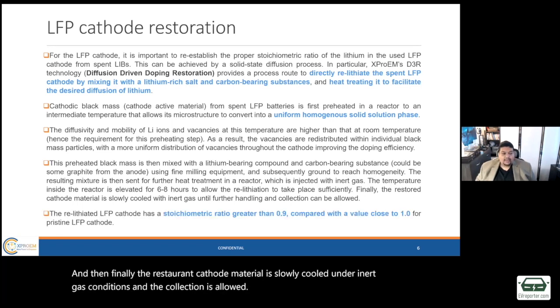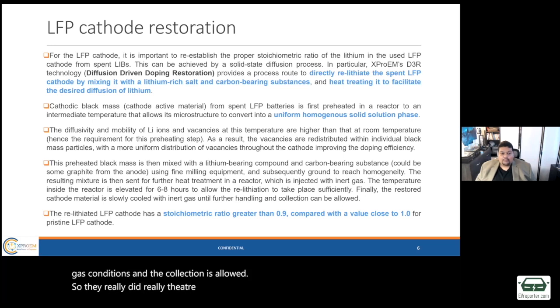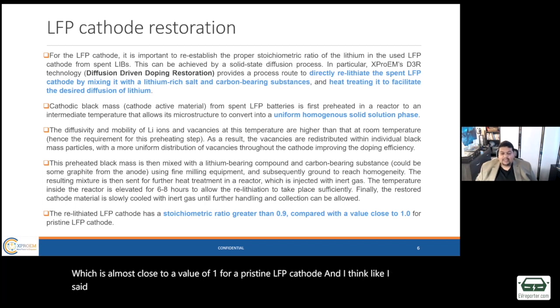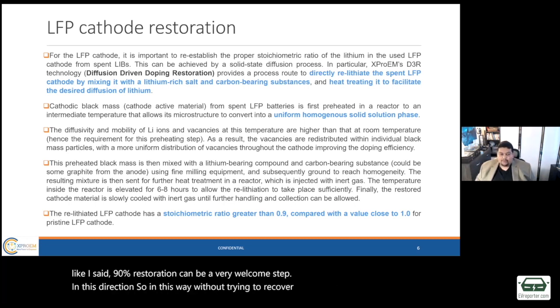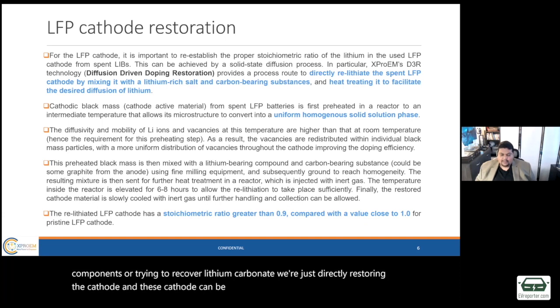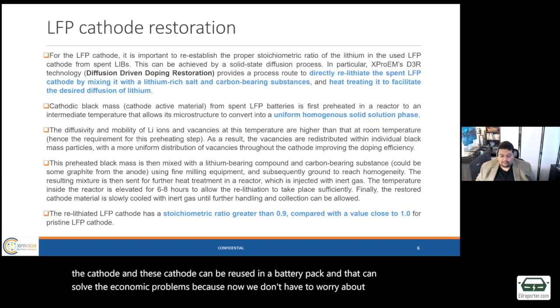So the relithiated LFP cathodes can have a stoichiometric ratio greater than 0.9, which is almost close to a value of 1 for a pristine LFP cathode. And like I said, a 90% restoration can be a very welcome step in this direction. So in this way, without trying to recover the individual components or trying to recover lithium carbonate, we are just directly restoring the cathode, and this cathode can be reused in a battery pack. That can solve the economic problems, because now we don't have to worry about individual component recycling.